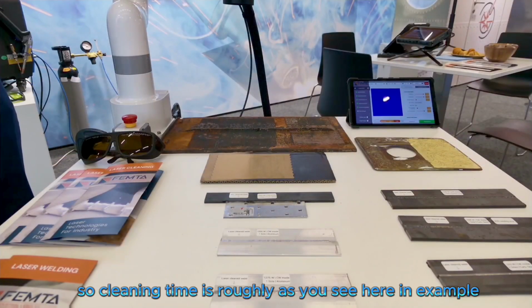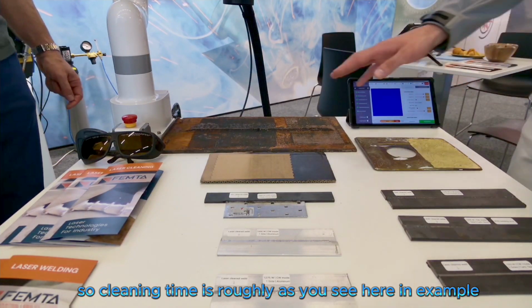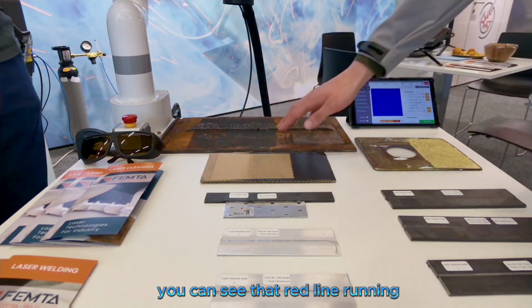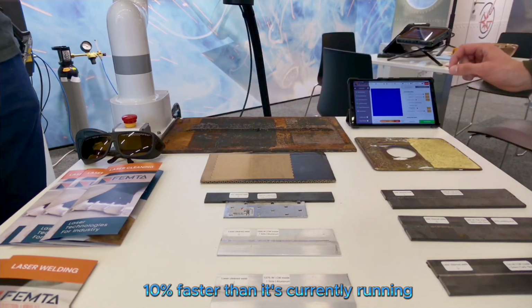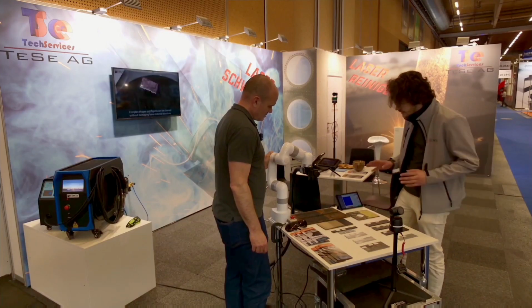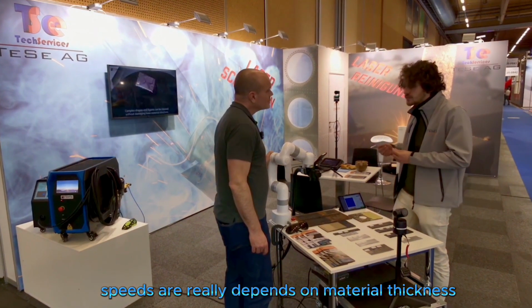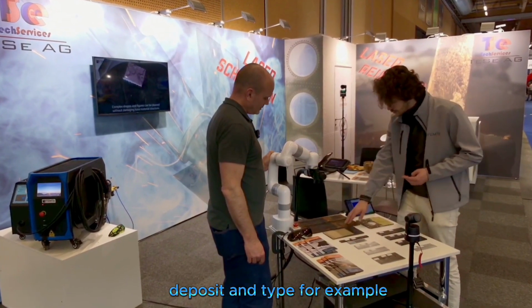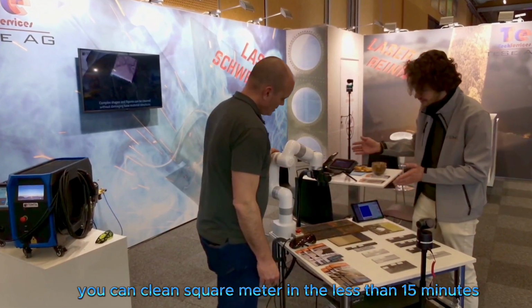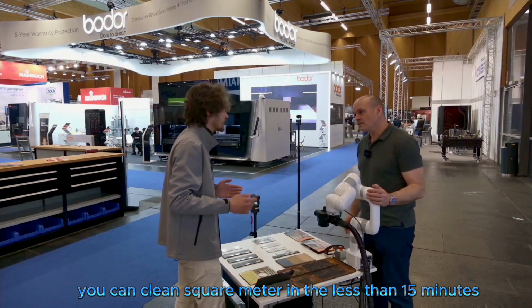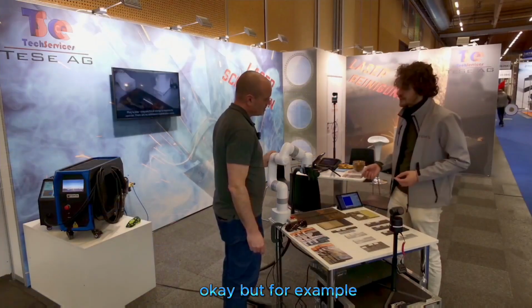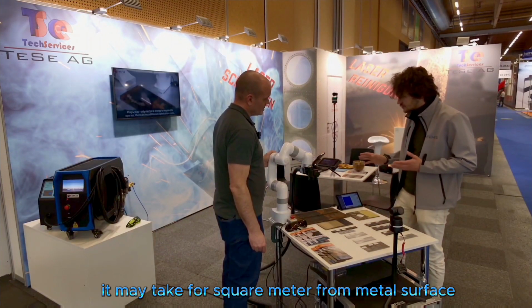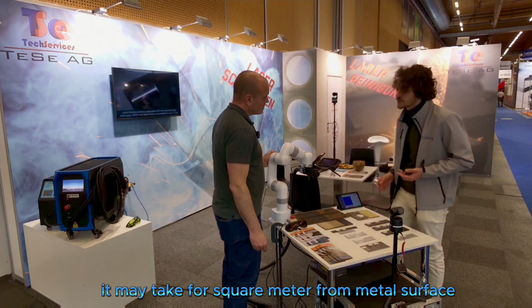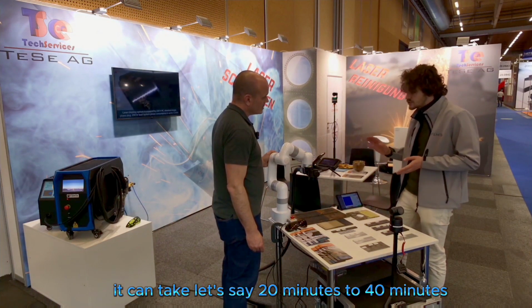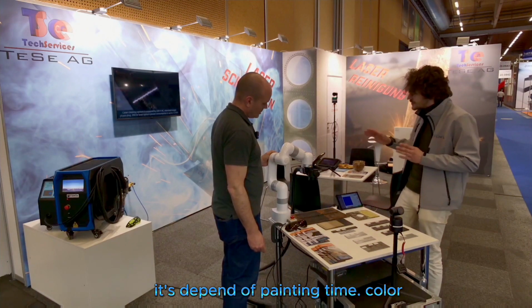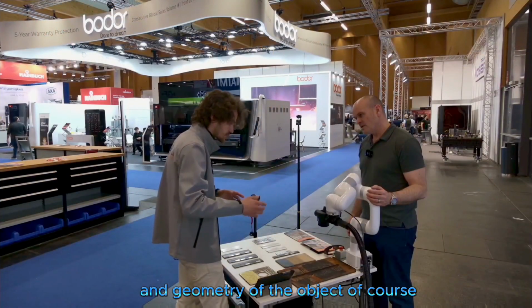Yes. So cleaning time is roughly, as you see here in the example, hopefully in the video, you can see that red line running. It can go a little bit faster, 10% faster than it's currently running. And cleaning speed per square meter really depends on material thickness, deposit, and type. For example, cleaning rust will be reasonably fast. You can clean a square meter in less than 15 minutes. But for thick paint removal, it may take, for a square meter of metal surface, let's say 20 to 40 minutes, depending on paint type, color, and geometry of the object.